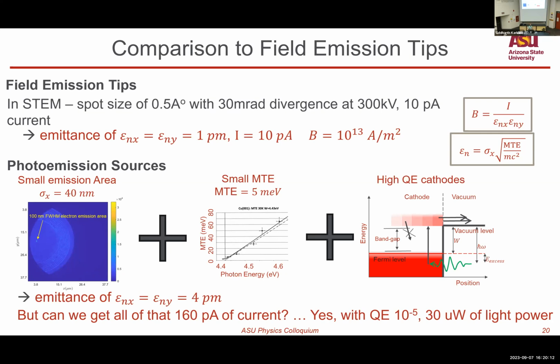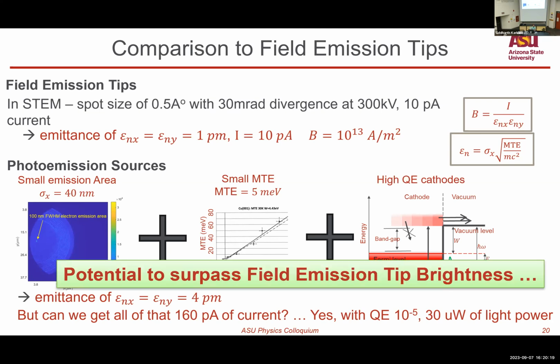It may not be trivial to do that, but I don't think it's impossible. And I think in the next 5 years, we'll probably be there. We really have the potential to surpass the field emission tip brightness. Another point here is the energy spread that we get from field emission tips is a few hundred millielectron volts. What we would get from this is 10 millielectron volts. So if you consider what we call the 6-dimensional brightness, it's way brighter than field emission tips.